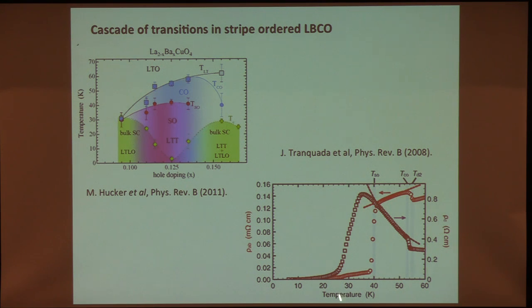By the way, this is a really weird material. It becomes sort of quasi-superconducting in two directions, but remains, this resistance is in ohm centimeters. This is in the more resistive direction. So it remains, well, you can see the resistance has an insulating temperature dependence and an enormous magnitude. So this thing is something that looks almost insulating in one direction and superconducting in two others, which is, well, impossible other than the fact that it's true. Okay.